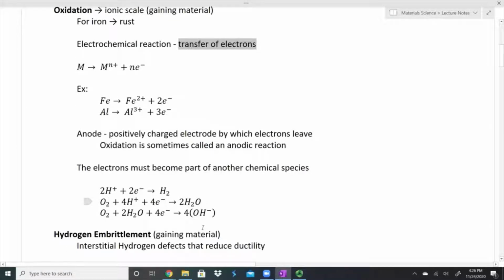And one other thing that metals do is we get hydrogen embrittlement. Again, this is a type of gaining of material. What happens is hydrogen is a very, very small molecule, and it's very, very easy for it to diffuse into materials. And so when there's enough hydrogen, it's going to diffuse into our metals. It's going to sit at the interstitial sites in our metal lattice. So these are interstitial defects. And what it's going to do is reduce ductility. And what does that mean? Well, when I reduce ductility, that means I'm increasing its ability to be brittle. So it's hydrogen embrittlement. It's getting brittle because of hydrogen.